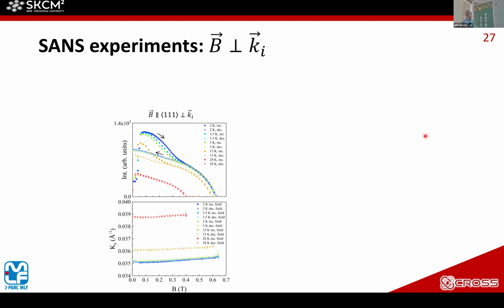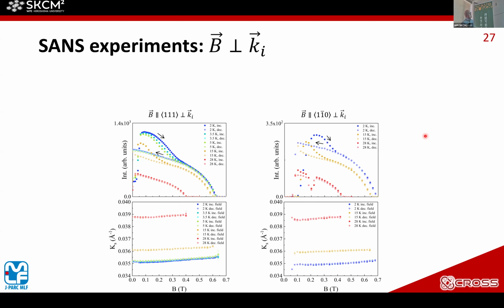Okay, then here shows the magnetic field dependence of the integrated Bragg spot intensity and propagation vector at several temperatures. As you can see, the propagation vector is independent of the magnetic field at all temperature regions. But here, the intensity of the Bragg spot shows funny behavior. When we apply the magnetic field, the intensity increases and decreases. But when we decrease the magnetic field, it follows the same intensity down to about 0.4 Tesla, but below 0.4 Tesla, there is a hysteresis. And this behavior was also observed in different magnetic field direction conditions like this.